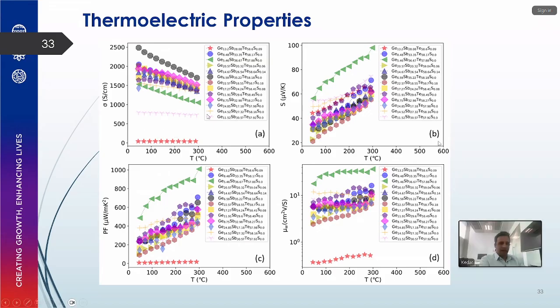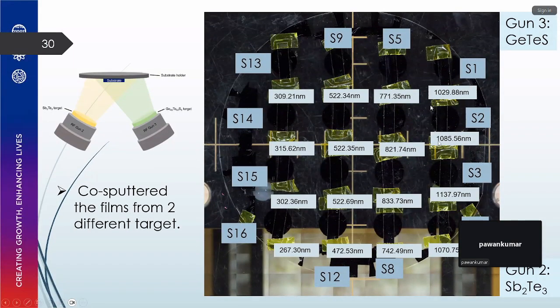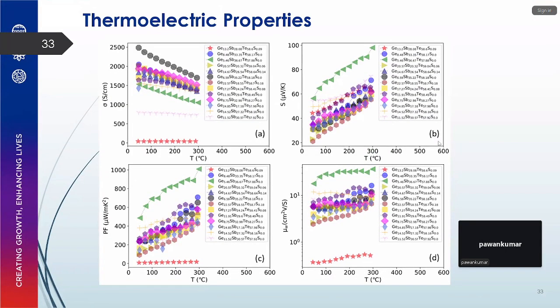So you cut them later, is it? I did not cut them. I used a specific holder. I put 2 samples here: one is the circle, and I also put in parallel a rectangular quartz substrate. It's stuck on top, so you have 2 samples, the circle as well as the rectangle sample. I directly put them in the ZEM-3 for measurement. What is the substrate? Quartz substrate only. We have a standard quartz substrate for the ZEM-3, a rectangle of 15 by 4 mm. So you can directly deposit the film and directly put it in the ZEM-3.